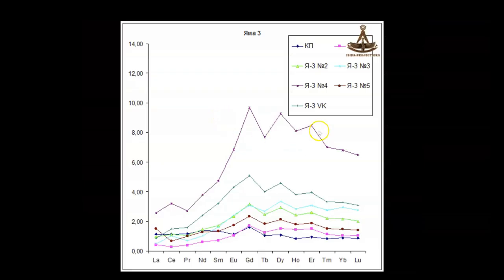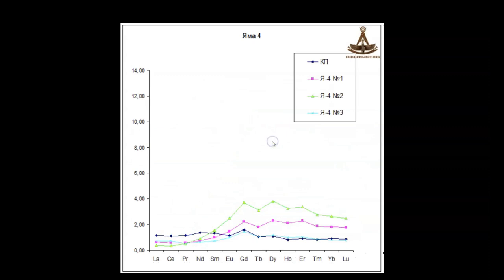Next up, a comparison of the rare earth elements in each pit, looking here at pit number 3, at the 6 different samples that were taken from that pit, compared to the control, which you can see down here at the bottom. They are comparing the concentrations of lanthanum, cerium, praseodymium, neodymium, samarium, europium, gadolinium, terbium, dysprosium, holmium, erbium, thulium, ytterbium, and lutetium. Sample number 4, which you can see here, from pit number 3, had the highest concentration of all of these elements. Next up, a comparison of the same elements from pit number 4 as compared to the control sample here, which you can see down at the bottom.